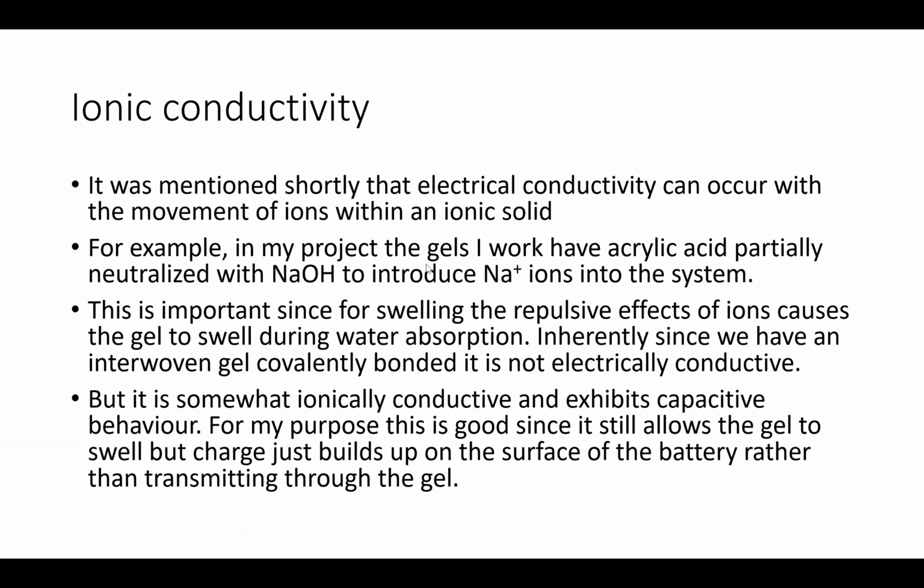In my project, the gels I work with have acrylic acid, and we partially neutralize this with sodium hydroxide. It introduces this partially neutralized acid that has these sodium ions in the system. And this is important since for swelling, the repulsive effects of ions cause the gel to swell during water absorption.